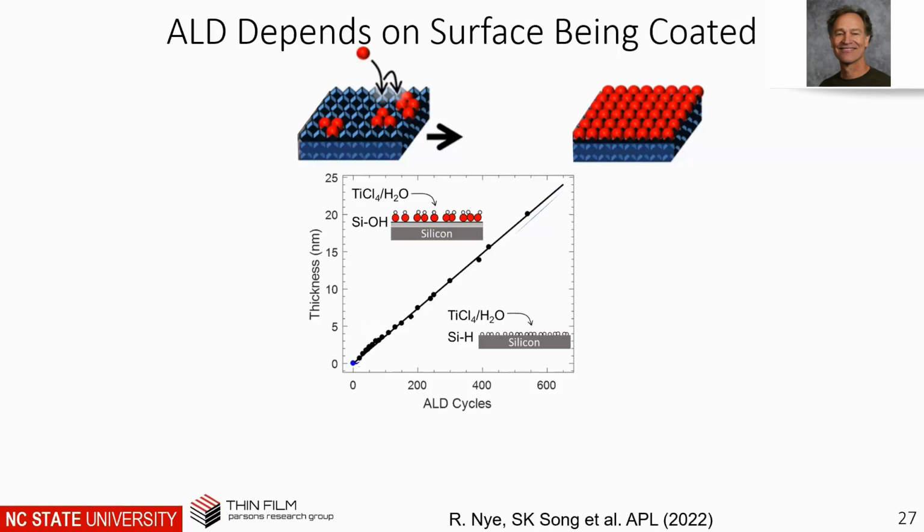The titanium tetrachloride doesn't really react with the silicon. And actually, the water doesn't really react quickly with the silicon either. So this surface is kind of inert. But if I keep exposing it, eventually it's going to react. So what I see is some sort of delay, and then, whoop, up it goes.